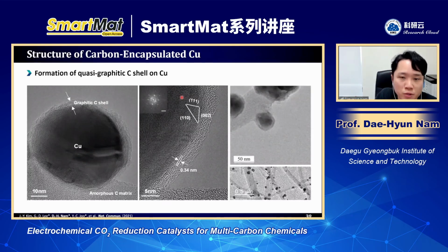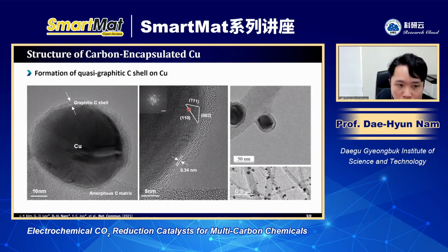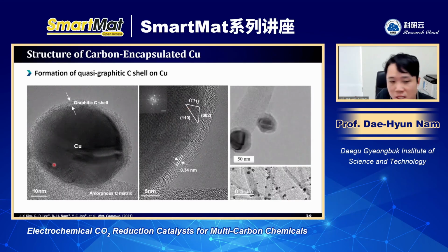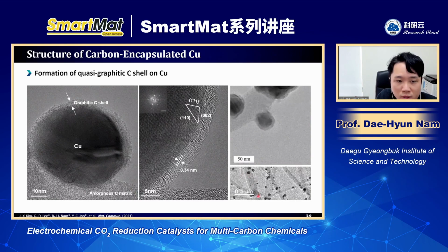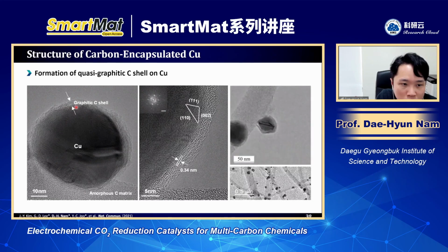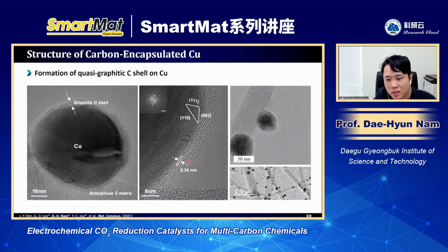So these are some results after applying this Boudouard reaction, doing the thermal calcination procedure. When you have these copper active sites located in the carbon support, this kind of carbon fiber, and if we look at the surface of the copper, by doing this gas-solid reaction, we could fabricate a quasi-graphitic carbon shell on the surface of copper. When you look at this TEM in the various directions, this carbon shell was coated semi-uniformly.